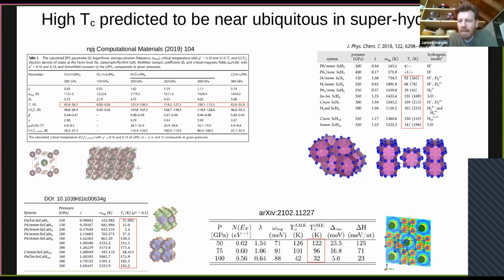And this occurs in a very wide range of different structures. There's, of course, some resemblance between many of these structures. They have some kind of cage-like appearance, but these are not identical structures. And this is somewhat in contrast to what my feeling is for how superconductivity has worked in other families of superconductors, right? The cuprates have this very similar structural motif of the copper oxide planes. The iron-based superconductors have these very similar planes, and the different members of the families are just different stackings of these planes with interlayers. The A15 superconductors all share this A15 structure, and if you move outside of that structure, it often leads to a drastic reduction in TC. In the case of iron-based superconductors, it's this structural motif that's important, and as soon as you move away from that, the superconductivity disappears.